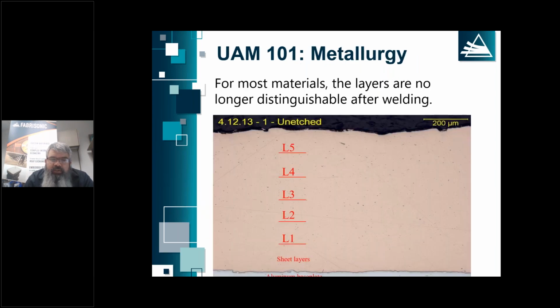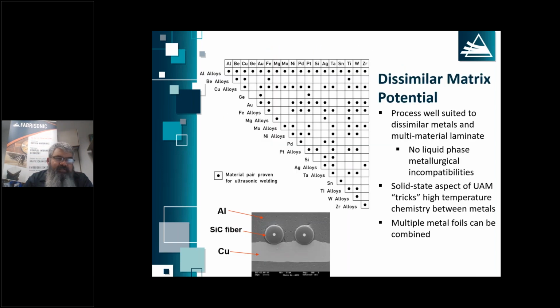So just from a quick metallurgy standpoint, this is a metallographic cross-section of copper printed onto aluminum. I think the thing to note here is without those red lines showing you where the interfaces are, you really wouldn't know where the interfaces occurred. It truly is a solid state welding process. We're getting 100% metallurgically bonded material. It's solid, it's dense, and we can mix materials all in the same buildup. That gives you a general idea. Certainly, as we make larger and larger parts, there's better ways to inspect, but just looking at it from a cross section, this gives you a good idea of the quality of the process.